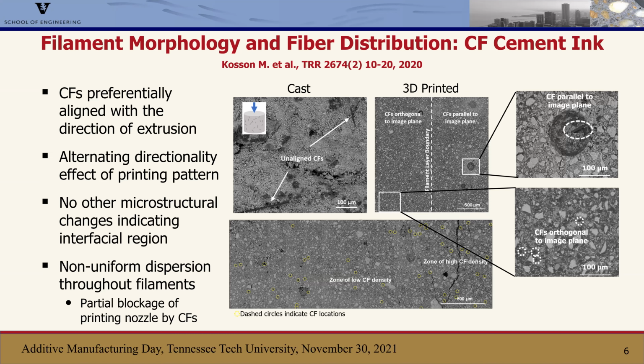Another important thing to consider was that we saw that there was a non-uniform dispersion of the fibers throughout the filaments, and it's thought that as you have these fibers align or not align, but not quite enough to cause a blockage, you can have fibers that have a tendency to come out all at once.